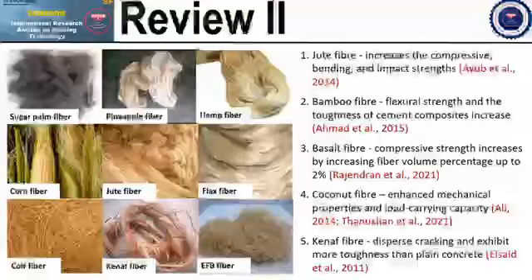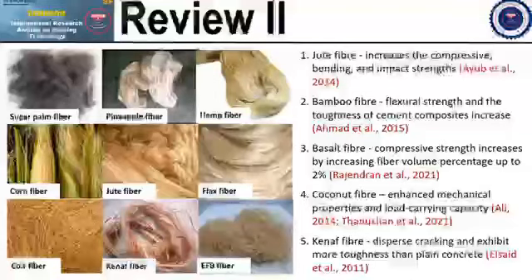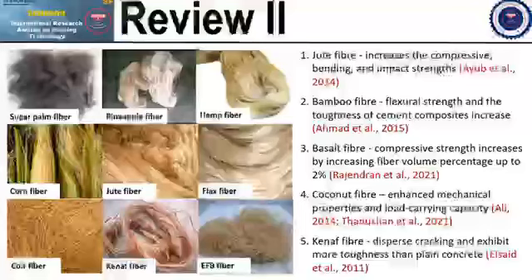addition of bamboo particles. Researchers also have worked on the reinforcement of basalt fibers in the high performance concrete and have done experimentation to test their tensile strengths, the Young's modulus, and compressive strength. It was observed that the compressive strength increases by increasing the volume fraction of the fibers up to 2%. Okay, above 2% weight fraction of fiber in concrete, the strength started to decrease. By the way, basalt fiber volume percentage had no significant effect on the elastic modulus values.